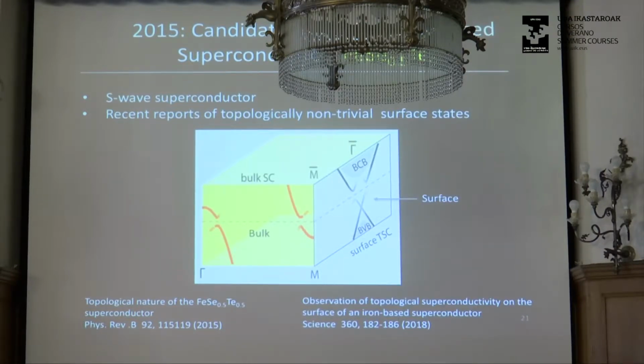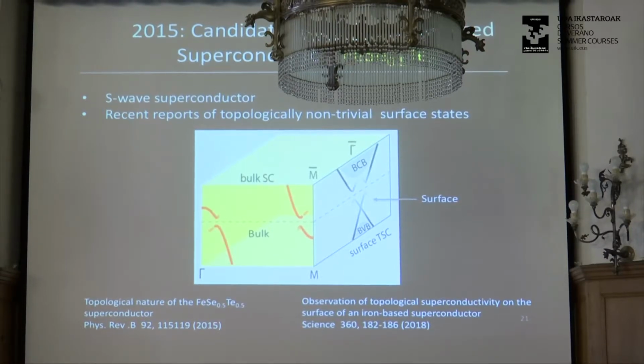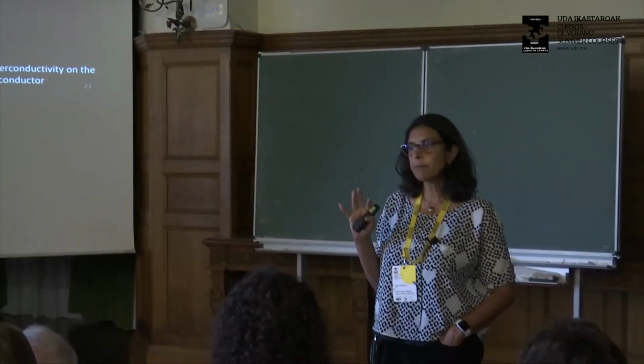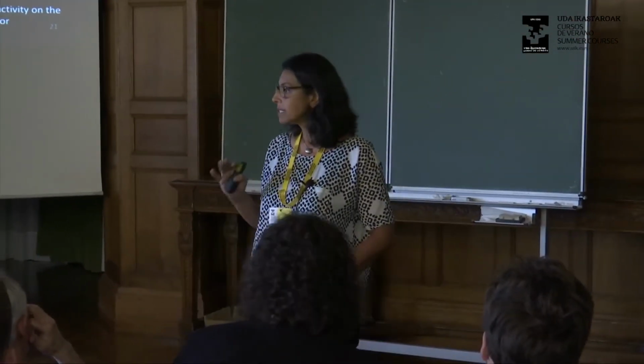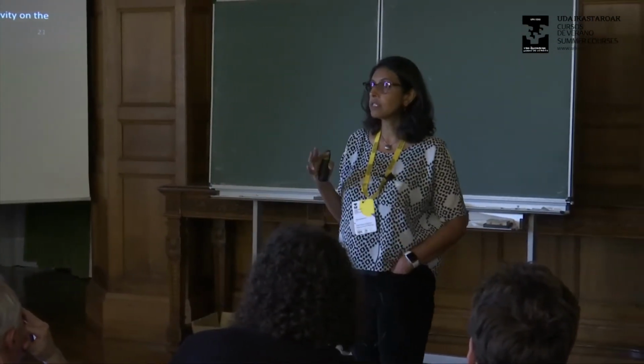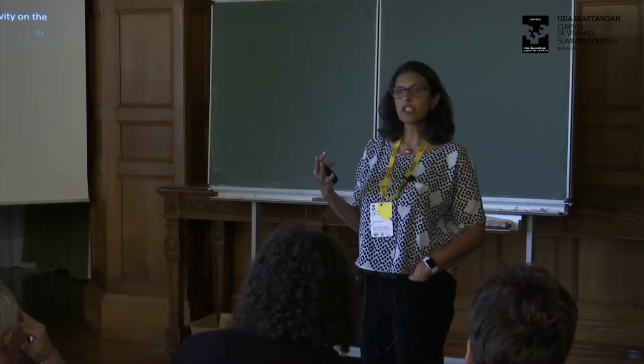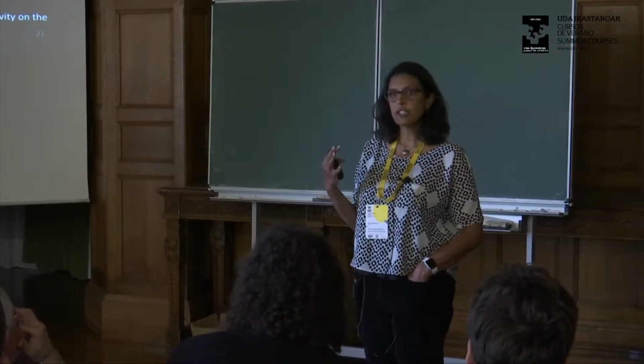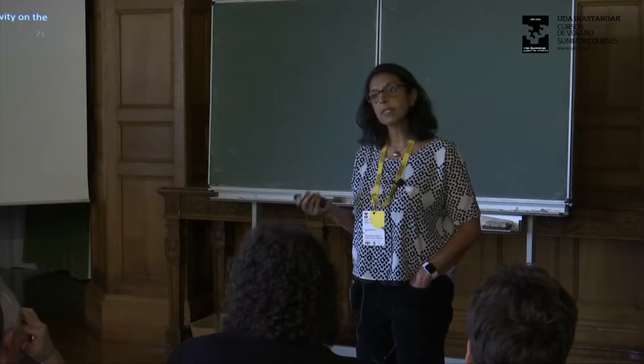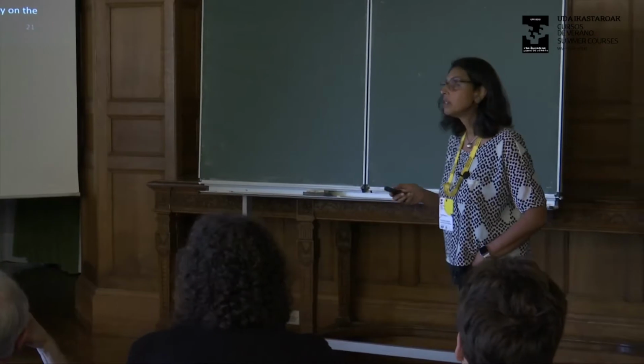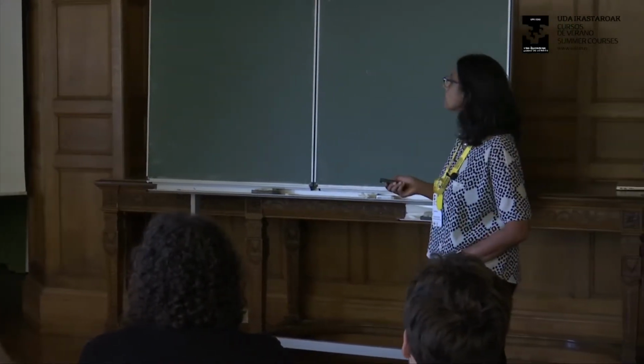So this is a pretty cool system because the TC of the superconductor is about 14 Kelvin. So you have a pretty high TC superconductor. Moreover, this is really important, this is an S-wave superconductor. It's actually possibly S plus minus, but still it's an S-wave superconductor. So this is what you need. So you have topologically non-trivial surface states potentially proximitized with an S-wave superconductor. So perhaps you could realize Majorana modes in this system.